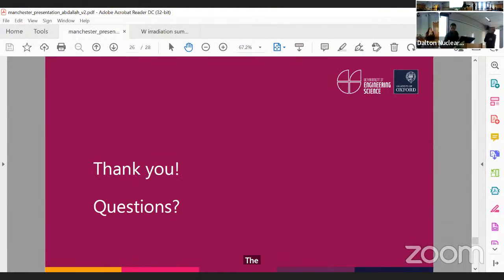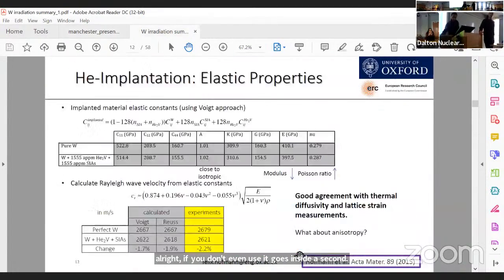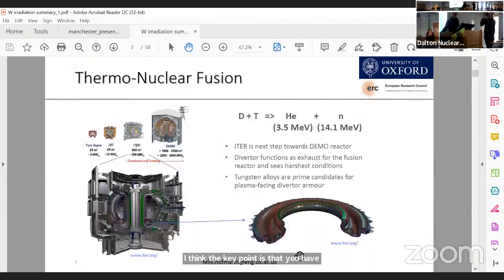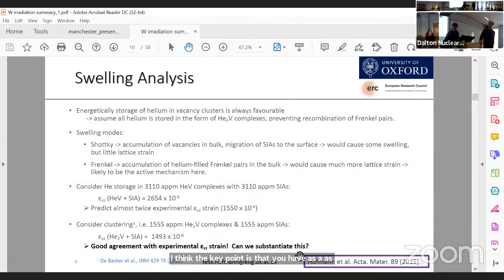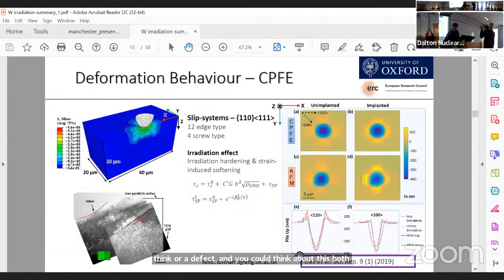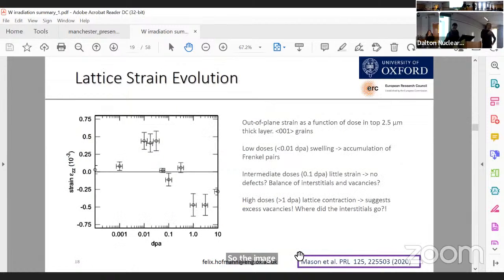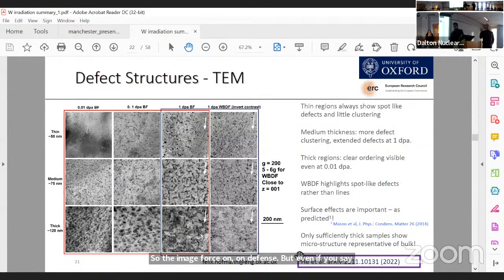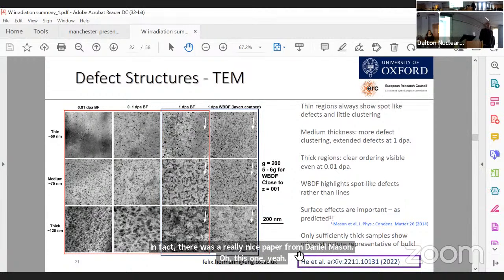I think the key point is that sample surfaces act as a strong sink for defects. You could think about this in terms of elastic interactions, so the image force on defects, but even if you say elastic interactions aren't that important, if your defects perform some kind of Brownian motion and they're close to the surface, they're quite likely to encounter that surface and will then be lost forever. So that's the difficulty. In fact, there was a really nice paper from Daniel Mason, this one here, 2014, where he did some OKMC simulations, and it just comes out of the simulations.